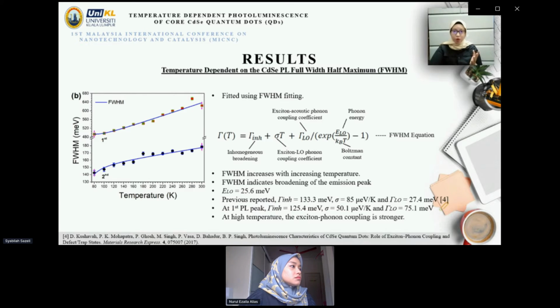temperature rises. The quantum confinement has caused the exciton acoustic phonon coupling to increase and the exciton LO phonon coupling constant to reduce, to 25.6 millielectron volt with respect to cadmium selenide quantum dots reported. Using 25.6 millielectron volt LO phonon energy, it showed that our sample has a slight difference from previously reported temperature effect toward cadmium selenide quantum dots PL emission broadening for the first PLP. Our fitting shows strong inhomogeneous broadening and agreeable LO phonon energy. This showed that the exciton LO phonon coupling mainly contributed to the homogeneous line width for quantum dots for this